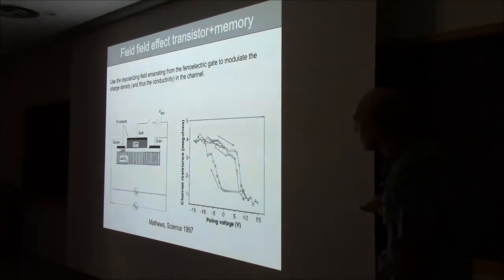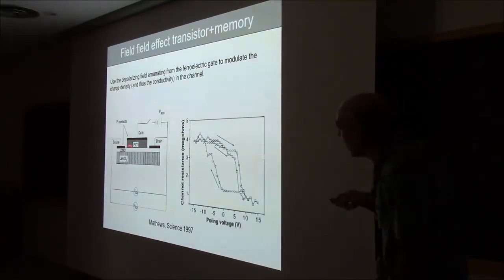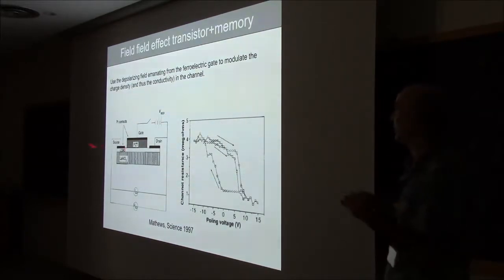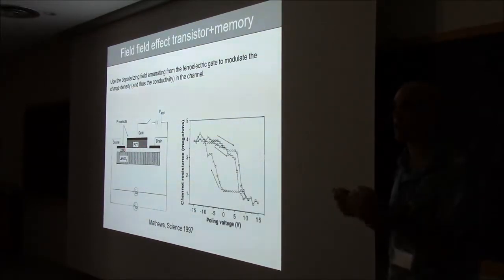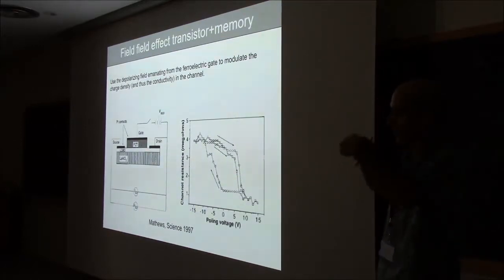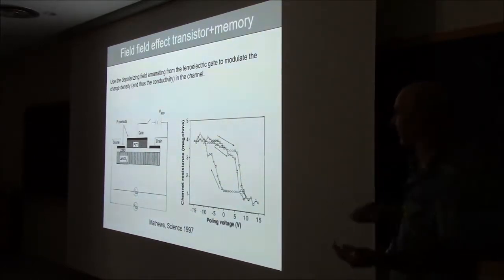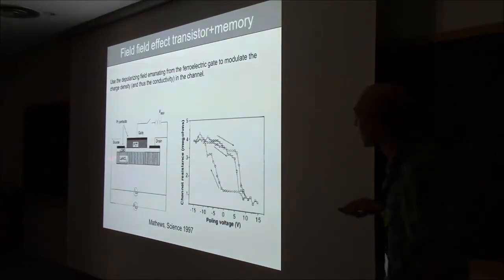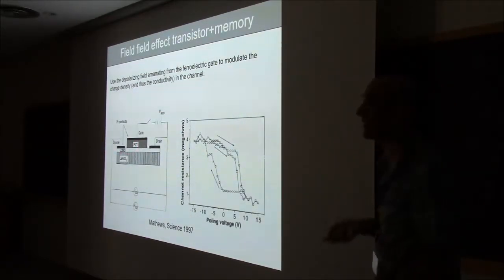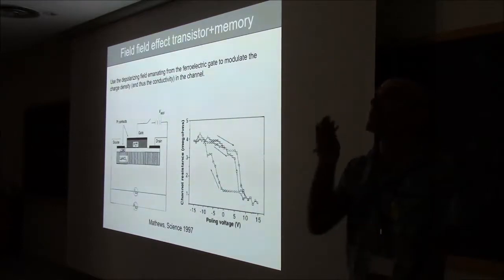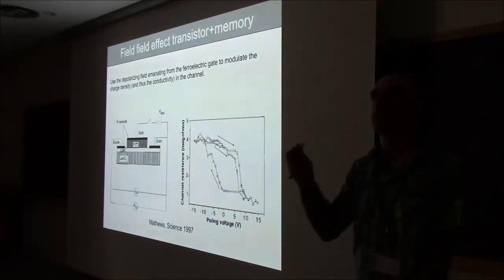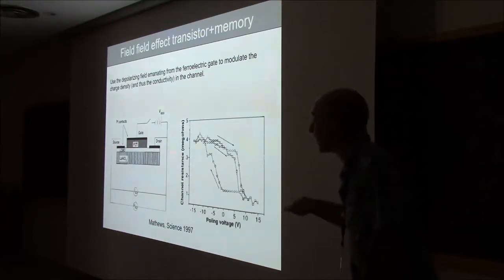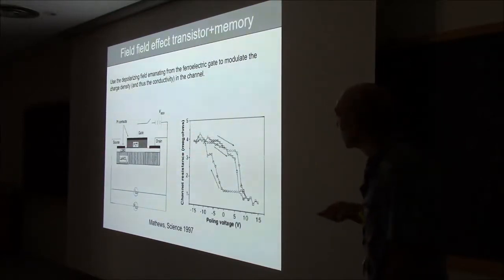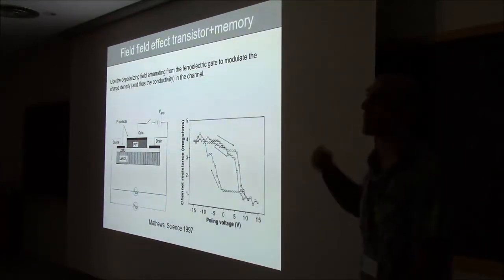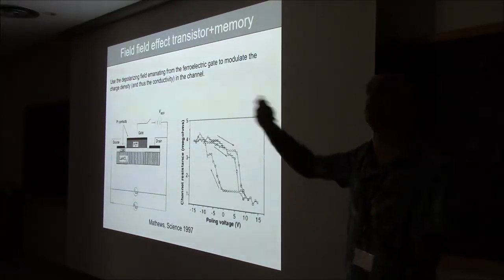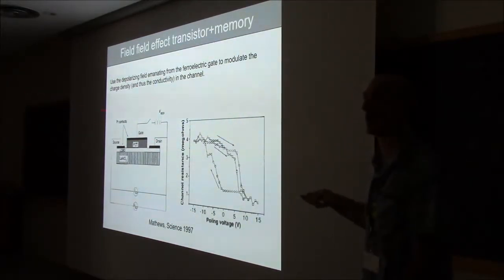strongly correlated electron systems. You can put a manganite in contact with your ferroelectric, and depending on the orientation of the polarization, that will create an electric field that's pointing down or up that has to be compensated by free charges. Those free charges will be provided by the manganite, and in doing so, those free charges will no longer be free, which means that the conductivity of your channel will go down. Okay, so you can modulate the conductivity of the channel using the polarization, the ferroelectric field emanating from your ferroelectric.